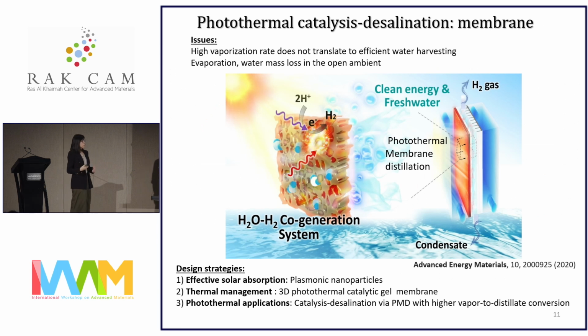So as we advance to the next phase of photothermal research, we reflected on the previous achievements and also lessons learned. While we have successfully demonstrated simultaneous harvesting of solar water and hydrogen, we noted that a high evaporation rate does not necessarily translate to efficient water harvesting, because evaporation is calculated based on water mass loss into open ambient instead of having an efficient water collection system.